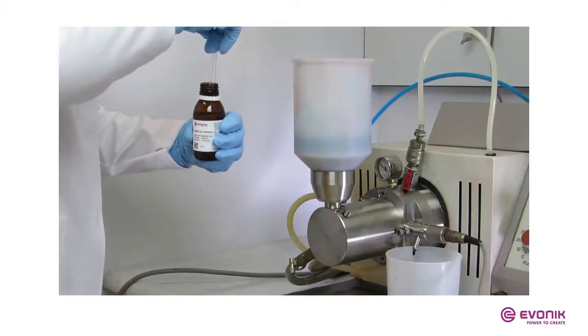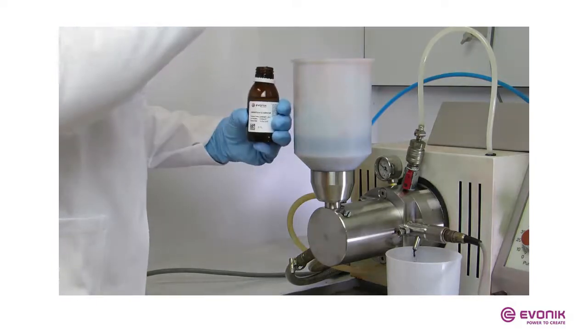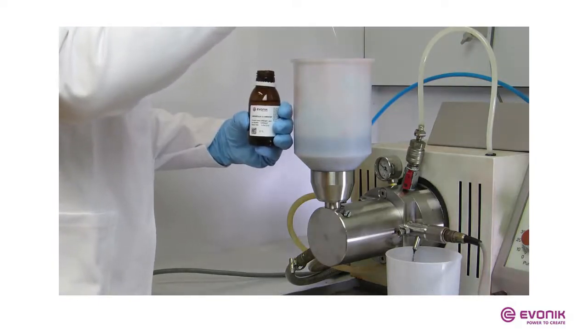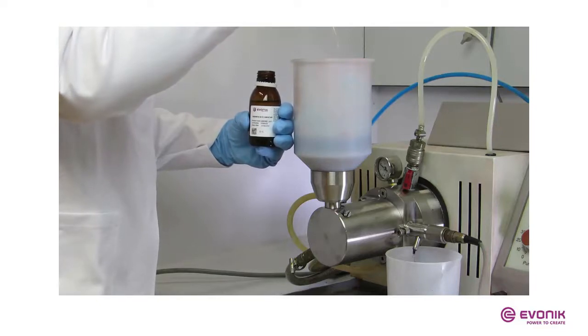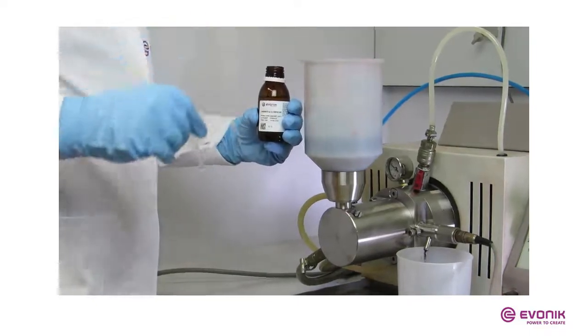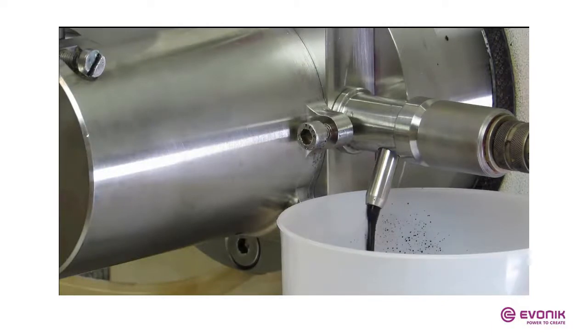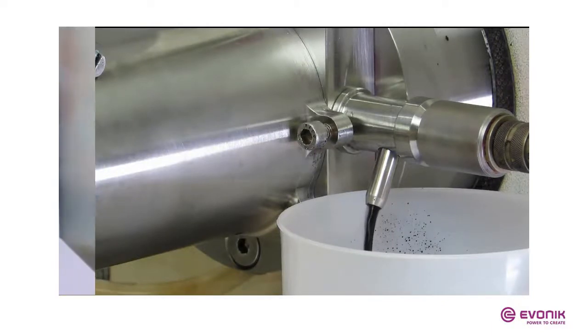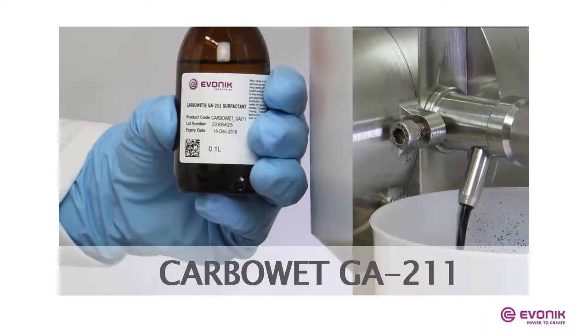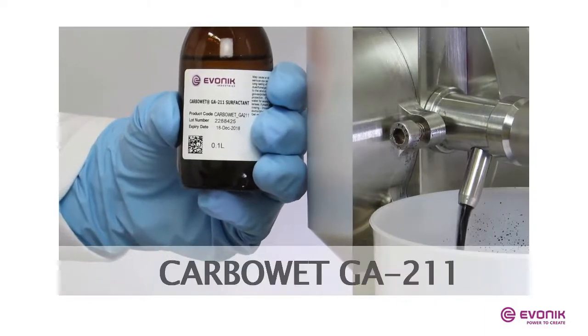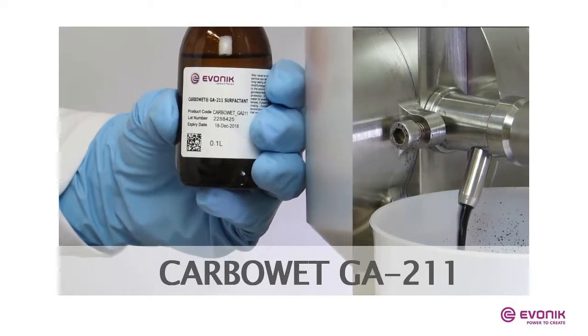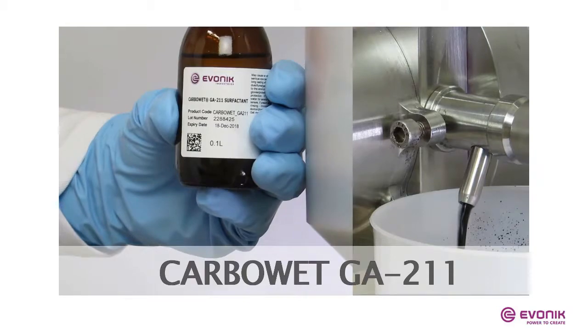Now we add to the premix a little bit of GA211, that is mainly about 1%. And now it has to go through the bead mill at first, and then you can see now the bead mill is running smoothly. The pressure is okay and the material is coming out of the machine.